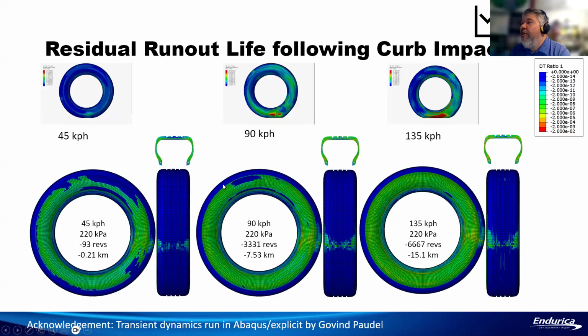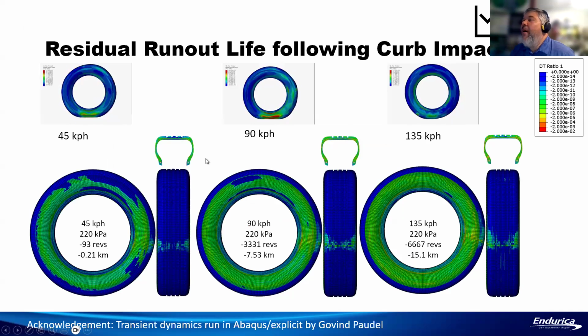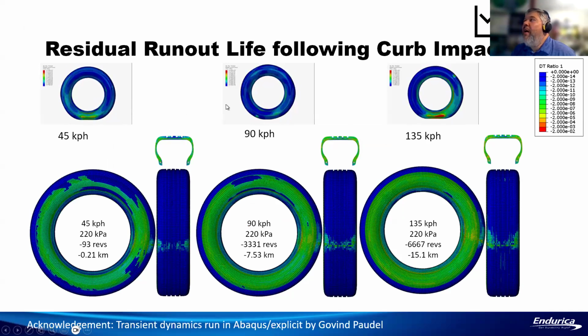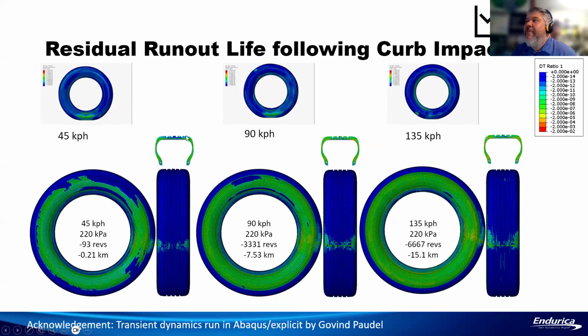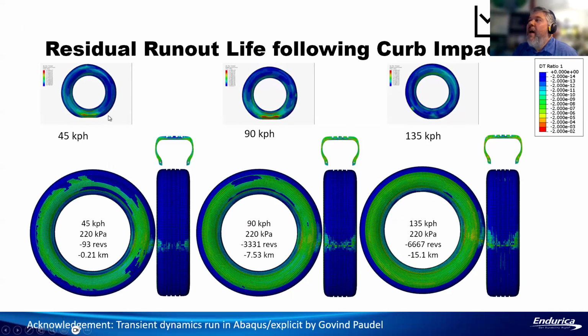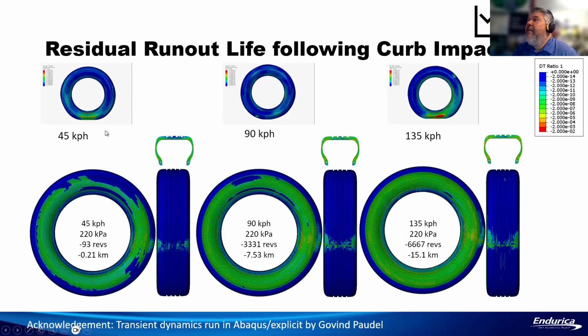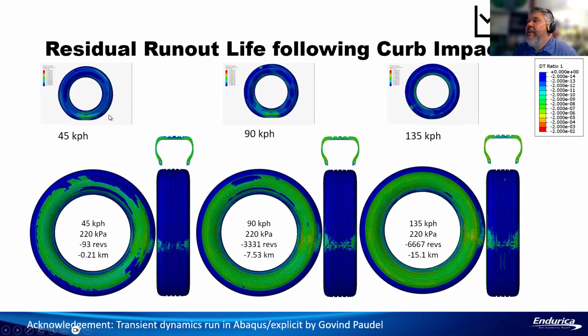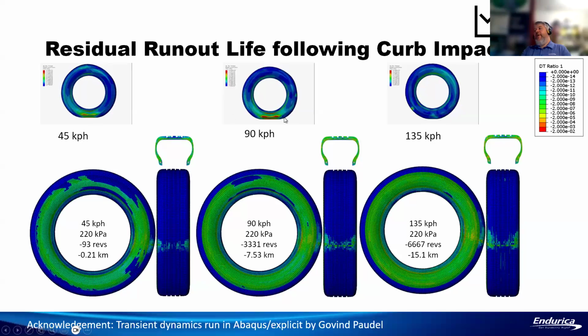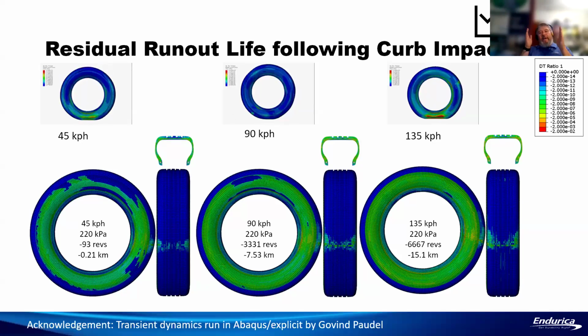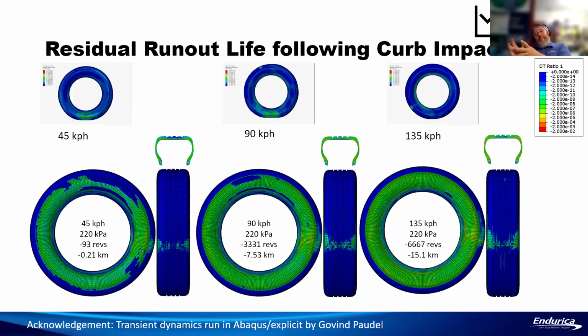And just as a further example, this is the same type of analysis looking at residual life, but this was a residual life analysis we did for a tire following a tire impact. So in the animations, you can see the obstacle, 150 millimeters tall, hitting the tire, setting up some waves around the tire. In this simulation, we did a half hour break-in, then we did the impact, and then we did a run out.